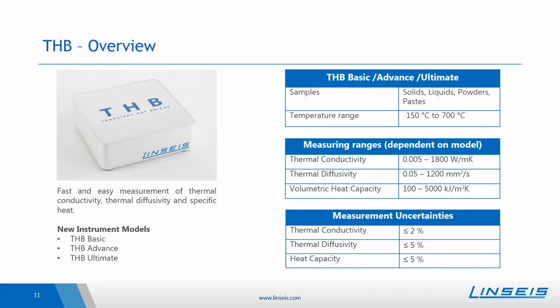Our transient hot bridge instrument is available in 3 different models: THB Basic, THB Advanced, and THB Ultimate. The difference between all of them is the thermal conductivity range. So the basic model can measure up to 5 watt per meter Kelvin, so especially suited for the polymer range and the building industry range. The THB Advanced can go up to 500 watt per meter Kelvin, so covering also a lot of different metals. And the THB Ultimate has the broadest thermal conductivity range and can go even up to 1,800 watt per meter Kelvin.